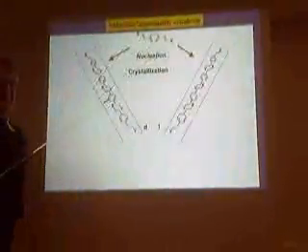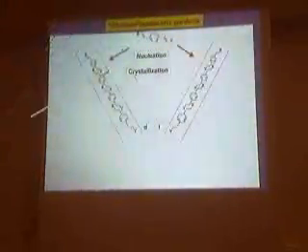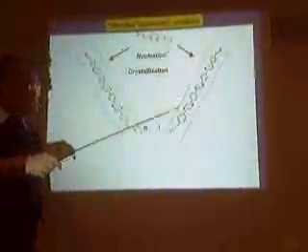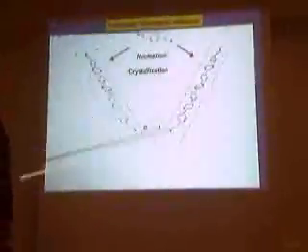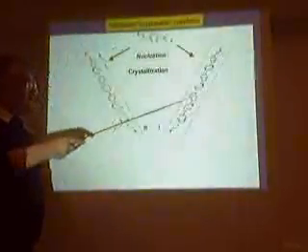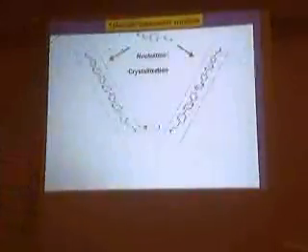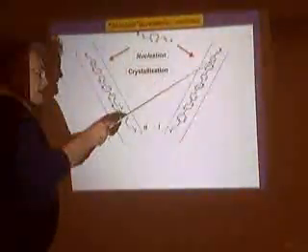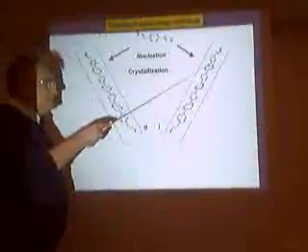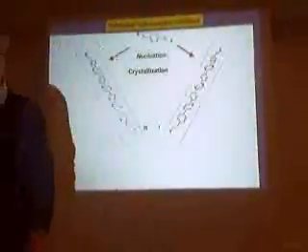We said, let us take a molecule which is non-chiral, because this molecule has a mirror plane. And at that time we thought about crystals which are enantiomorphous. Can we design such a system which will crystallize in a specific crystal structure, such that the molecules in the crystal will be related only by translation? If they are related by translation, this is a polar crystal, an enantiomorphous crystal, where the double bonds between X and Y will be in good proximity for reactivity, about 4 Angstrom. This is what Gerhard Schmidt confirmed in the early days, and we knew a little bit about the system, therefore we wanted to go to this particular system.